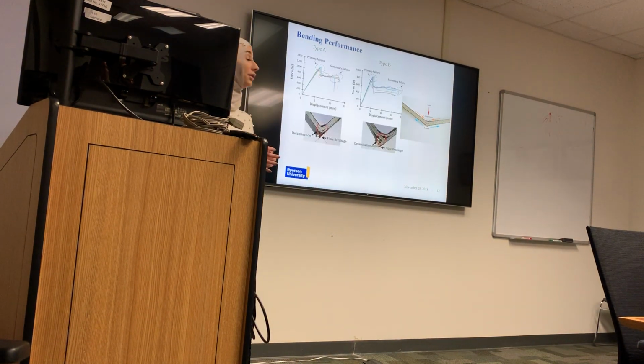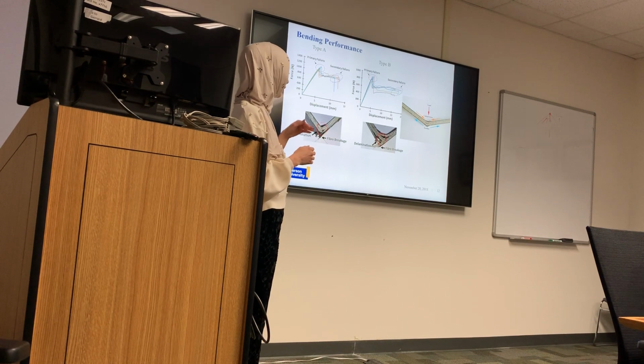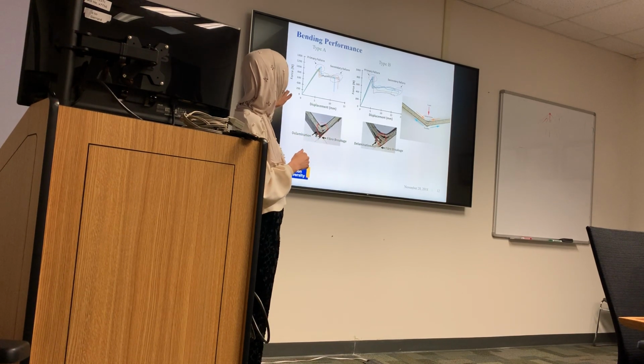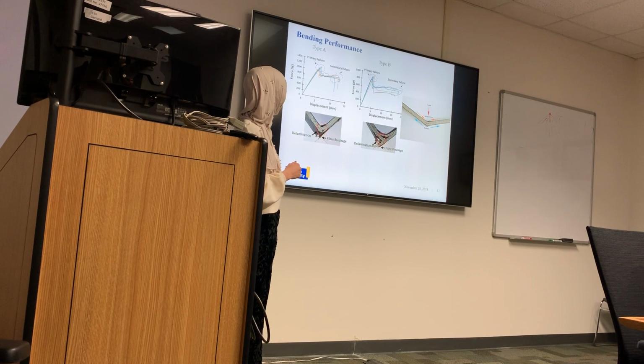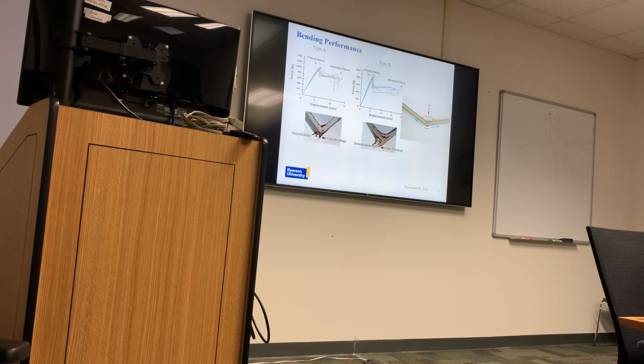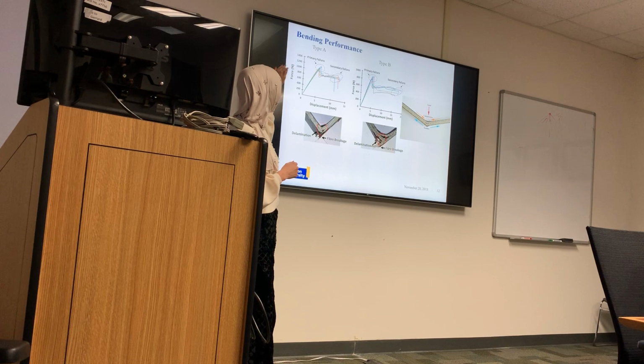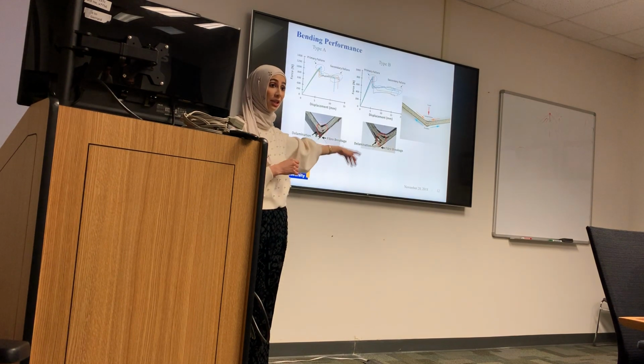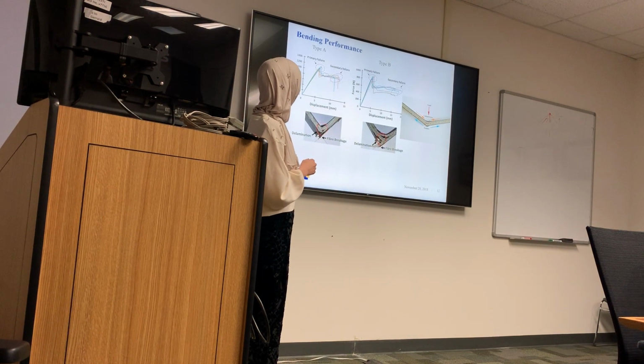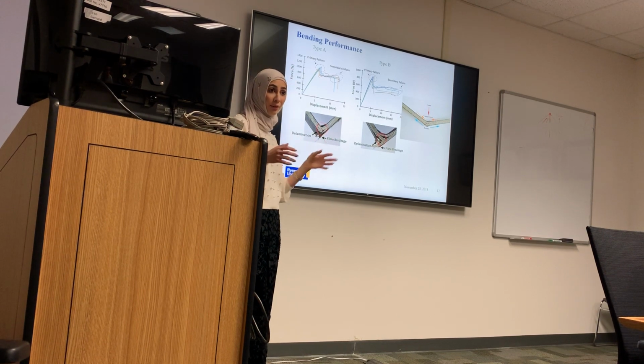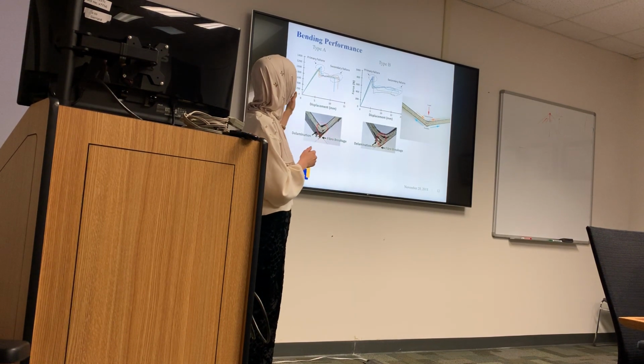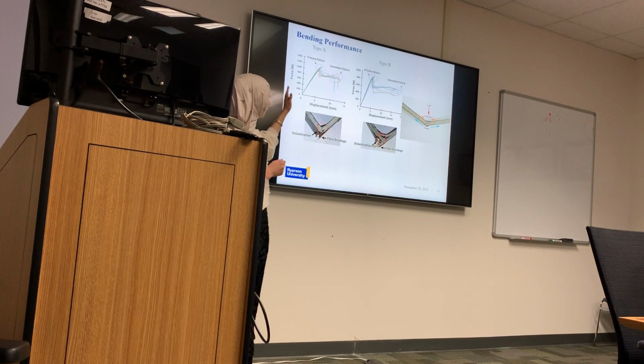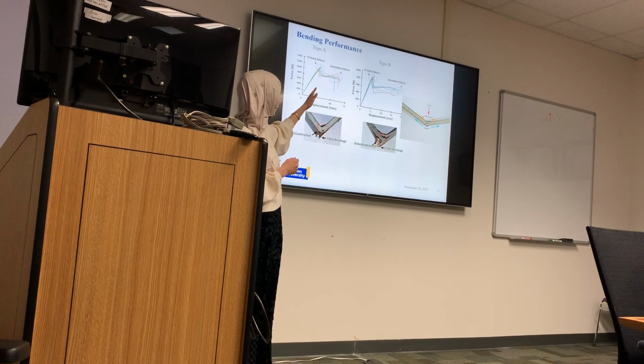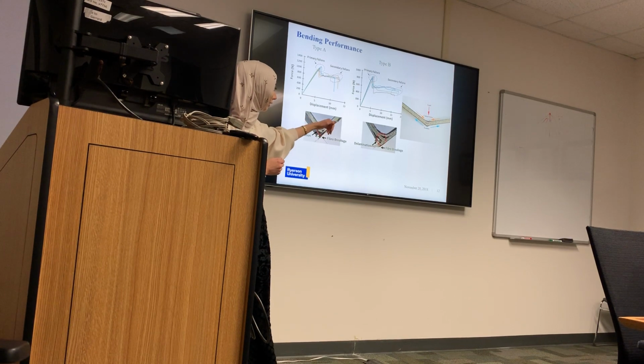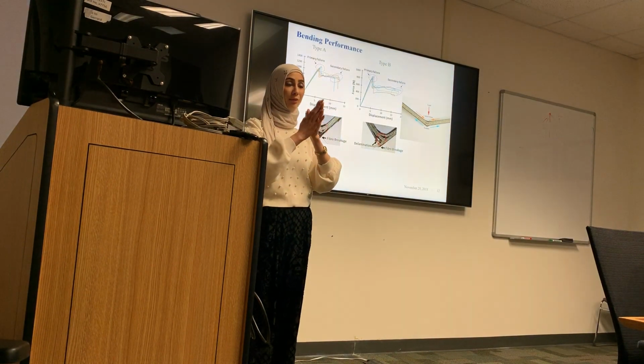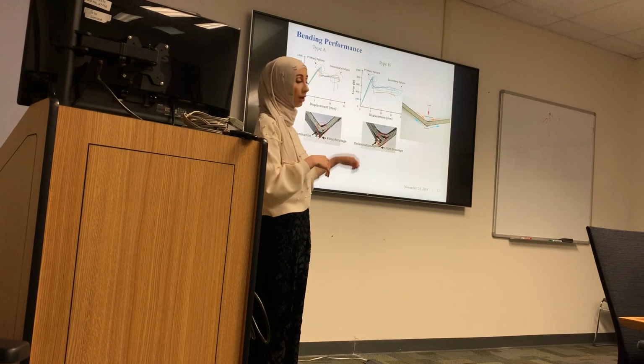We see here the 2 results for type A and B. We can divide that into 3 regions. We see an elastic region where, whenever we increase the force, the displacement increases up to a certain point where fracture starts in the tension layer. Then the force will drop about 20 to 25%. You see that the flax fiber core is able to hold the force for quite a bit of time until the last or final failure, in which the crack propagated from the tensile side up to the compression side.